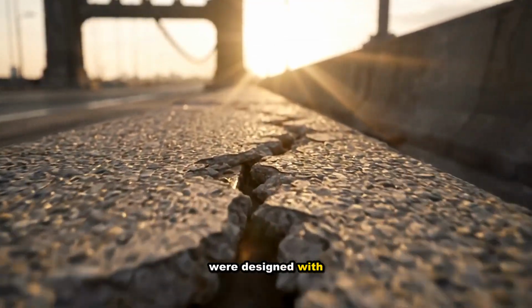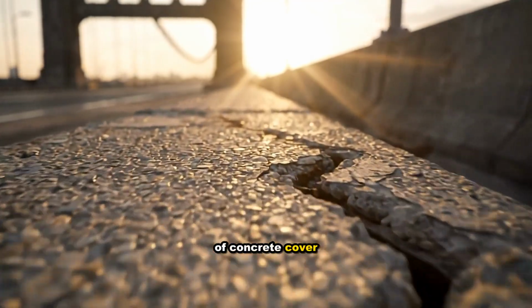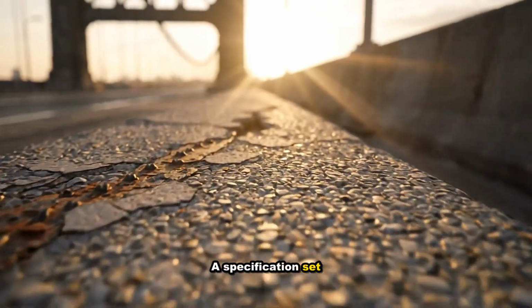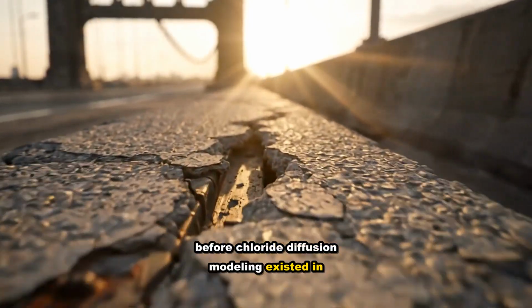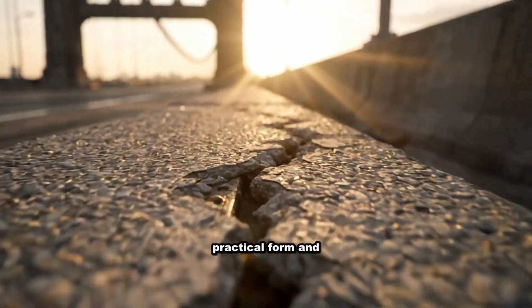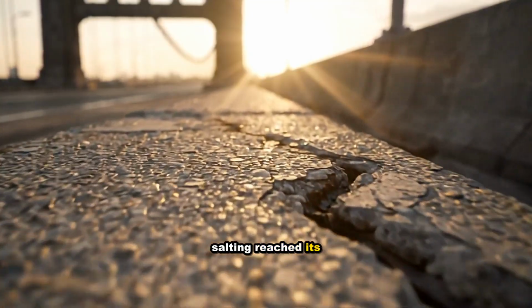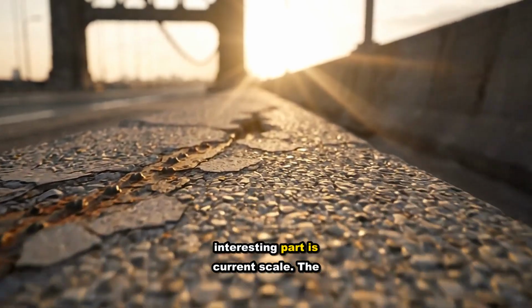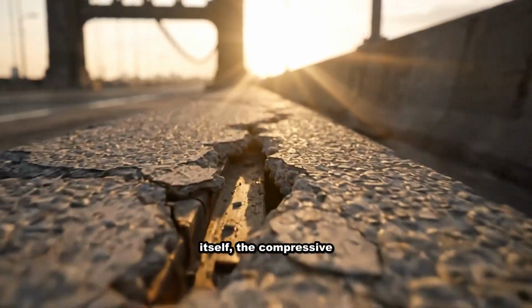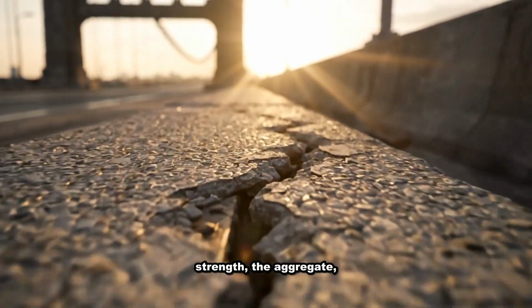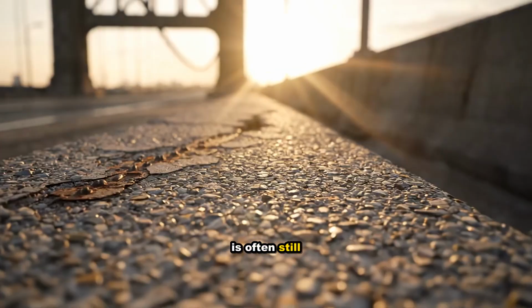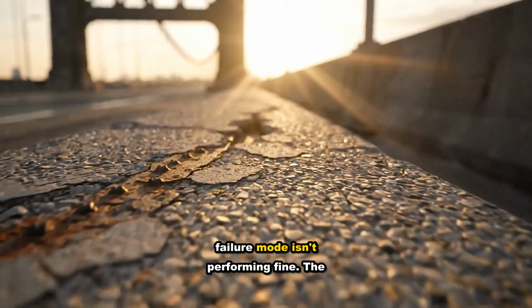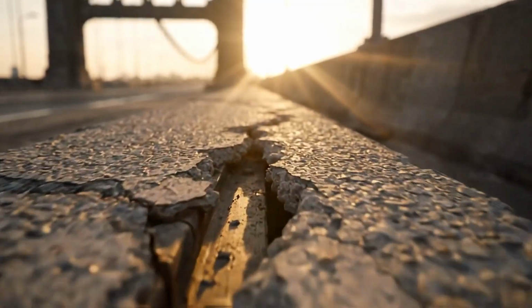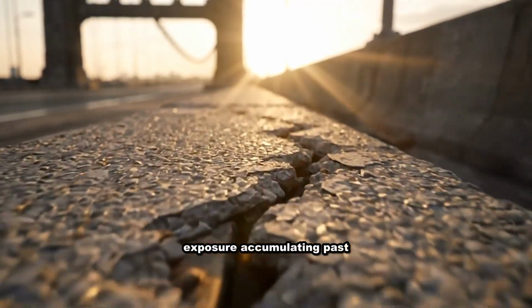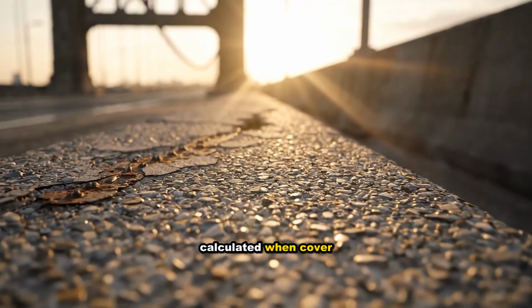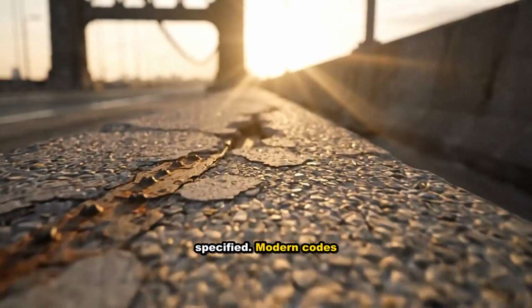Those structures were designed with roughly 1.5 inches of concrete cover over the rebar, a specification set before chloride diffusion modeling existed in practical form, and before winter road salting reached its current scale. The interesting part is that the concrete itself, the compressive strength, the aggregate, the mix design, is often still performing fine. The failure mode isn't the concrete aging. It's the salt exposure accumulating past a threshold nobody calculated when cover depth was originally specified.